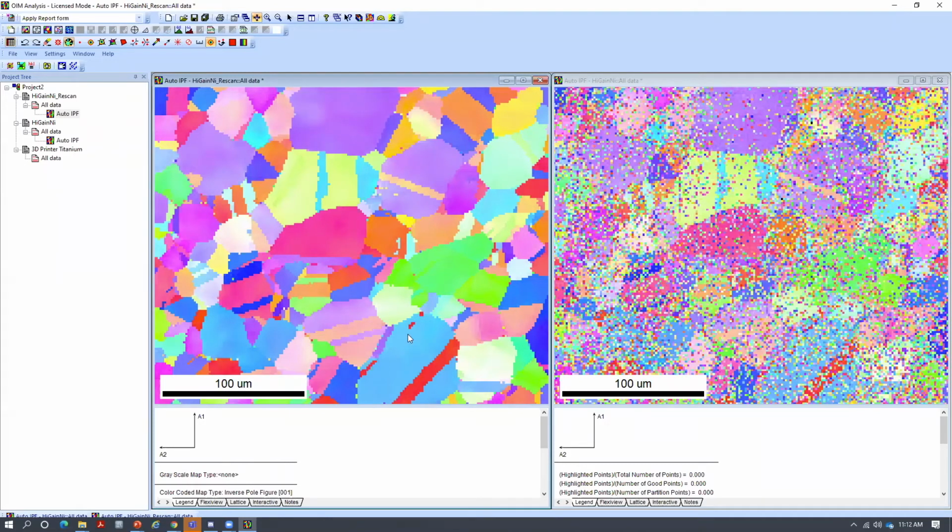And the reason we're losing it is pretty simple, right? If I had, let's say, a 1 or 2 pixel area that made up that single twin, if I use NPAR, NPAR can push that boundary over on both sides. And then suddenly that thing that was 2 pixels wide is now gone. That's actually exactly what happens here. Also what happened here in this case, where again another grain boundary is lost. But here you can see this one right here is about 3 grains across, and it's not lost.